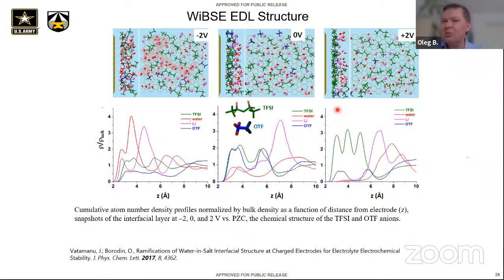To me that is very interesting, because that indicates that there are mechanisms of selective electrosorption which can be utilized, maybe even beyond the lithium battery field, for preferentially changing surface properties as a function of potential. And clearly, when water gets pushed out, there is a lack of water coming in. Lithium still needs to get desolvated from water and solvated by TFSI in order to intercalate. But that minimizes excess water, and especially the very small fraction which is free water, for the oxidation. And free water oxidation-wise would be expected to be preferential, right? So that's where removing free water is nice.